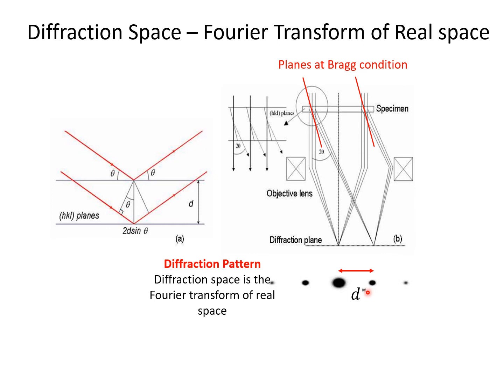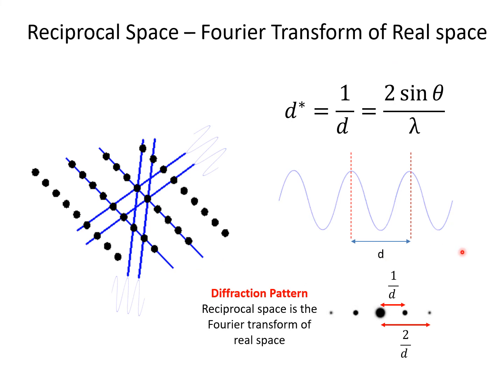But basically, in the case of a Fourier transform, it means that we're converting a spatial variation. If we have a spatial variation in electron intensity, a real spatial variation that exists because of the arrangement of atoms, that spatial variation transforms into a reciprocal variation in diffractive intensity in diffraction space.